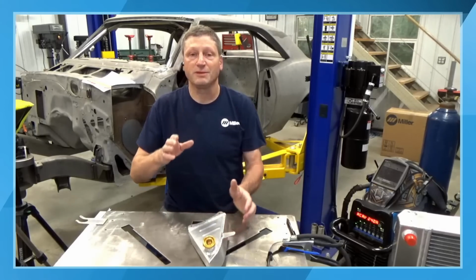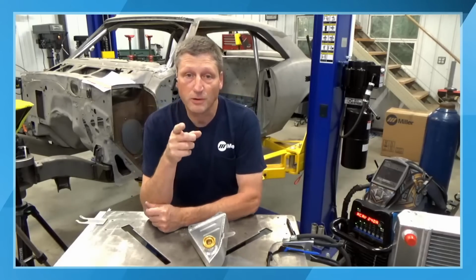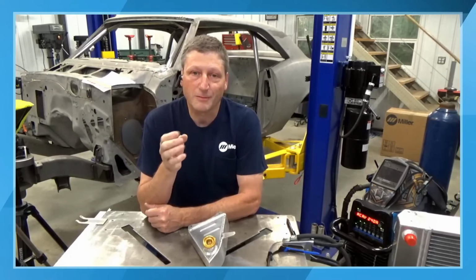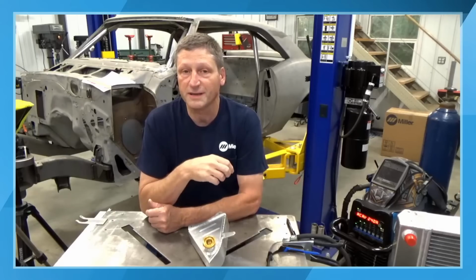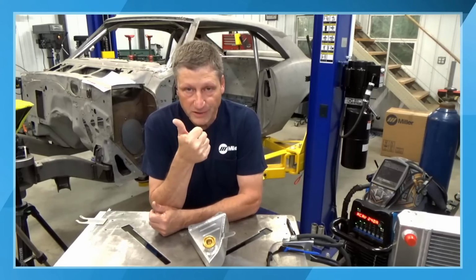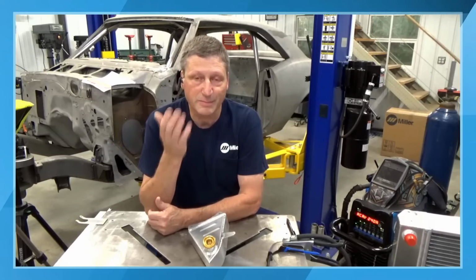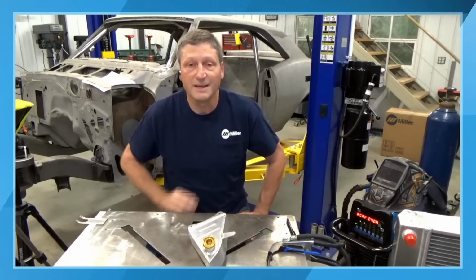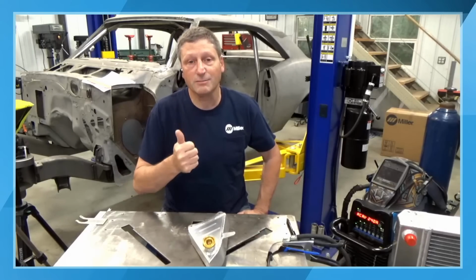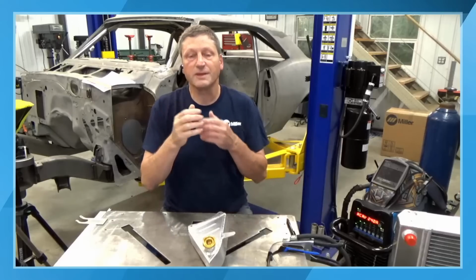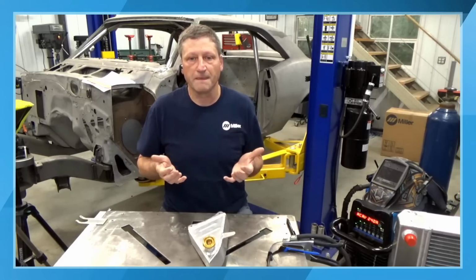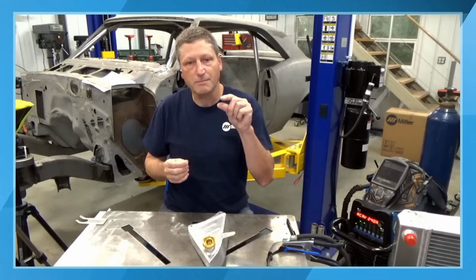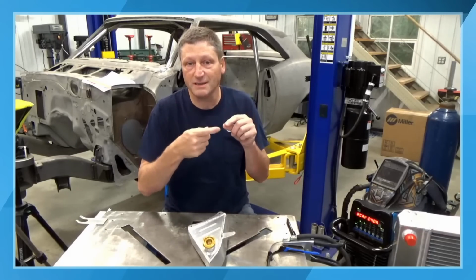A good example of this is the turbo inlet charge tubes, right? A lot of those charge tubes are 6061. And I see people welding them with 5356 filler metal quite often, and they look beautiful. However, they're under pressure and they're in a high heat application, and they wonder why their welds are cracking. It's because the 5356 material isn't suited for high temperature. And because the charge tube is thin, there's something called base metal dilution. Base metal dilution is how much of the base metal, when you're welding it, is melting in with the filler metal.